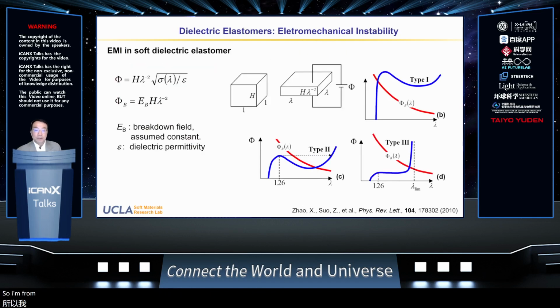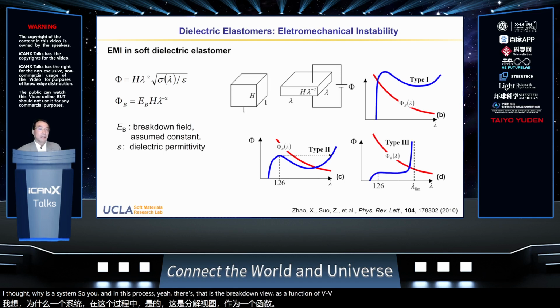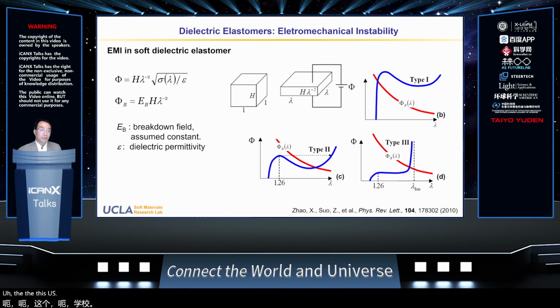So Professor Xuanhe Zhao and Zhigang Suo introduced this beautiful theory to explain the electromechanical instability. Basically, they categorize dielectric elastomers into three different kinds. Type 1 is a stiff one. And in this chart here, the red curve is the breakdown field as a function of the stretch ratio. Okay, so assuming the breakdown field is a constant, then the breakdown voltage varies with the stretch ratio.